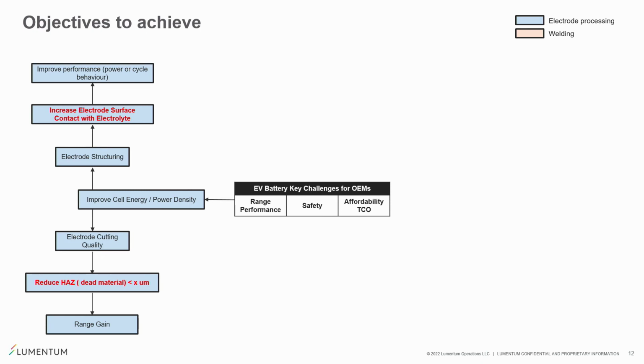The second part, which enables power now, is more on the electrode structuring. What you do, and you saw that in the previous slides, is create a pattern, small holes or other features within the electrode to increase the wettability of the electrode, the contact surface area between the electrode and the electrolyte. And by doing that, you improve further the performance in terms of power, in terms of cycling charge as well.